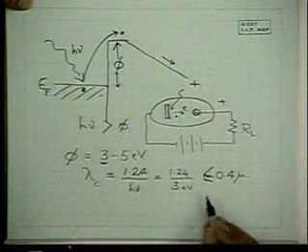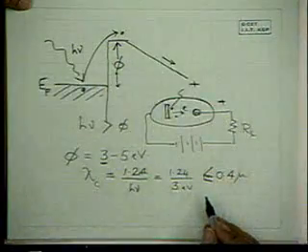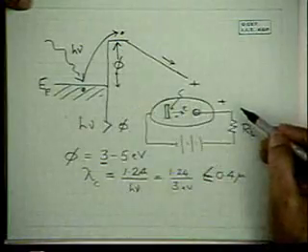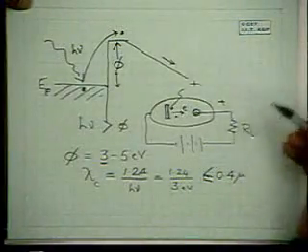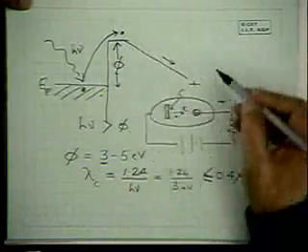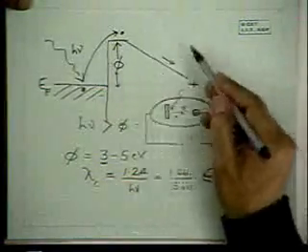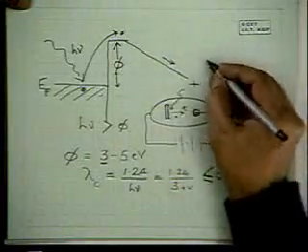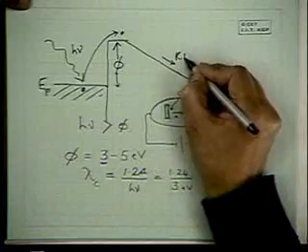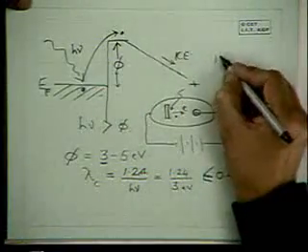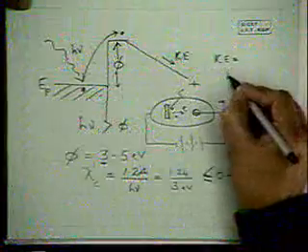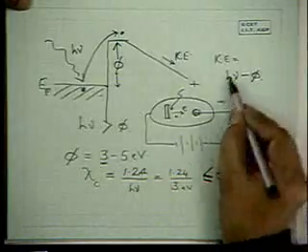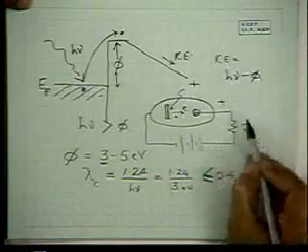Okay, so this was the state of the art in the 1910s and 20s, when metals, typically tungsten, molybdenum, etc., were used. Of course, the working of this device is based on the photoelectric effect as described by Einstein. The kinetic energy of the electron is obviously equal to h nu minus phi. There's a cutoff at the value h nu equal to phi.